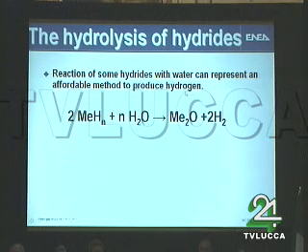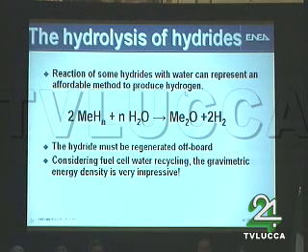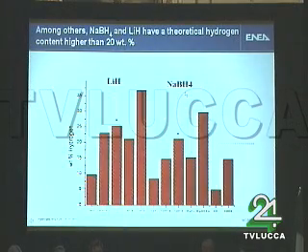Okay. Another way to meet DOE goals is the hydrolysis of hydrides. The reaction of some hydrides with water can represent an affordable method to produce hydrogen, especially if we are able to recycle the water from the fuel cell. In such a case, the gravimetric energy density is very impressive. The hydride must be regenerated off board. Among others, lithium hydride and sodium borohydride have a hydrogen weight percent higher than 20%,